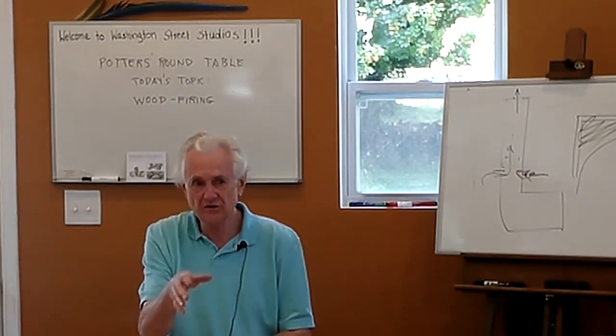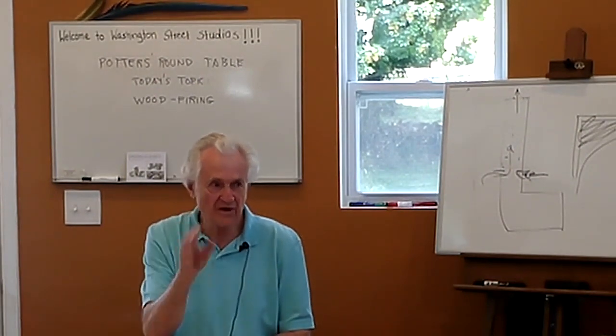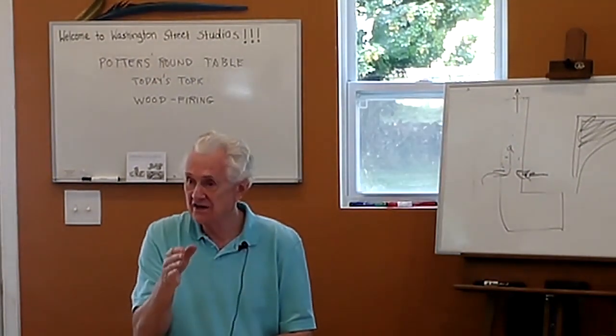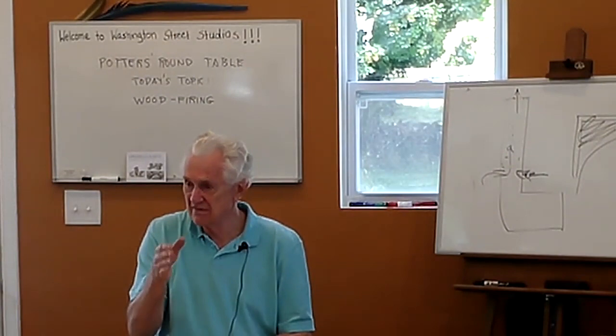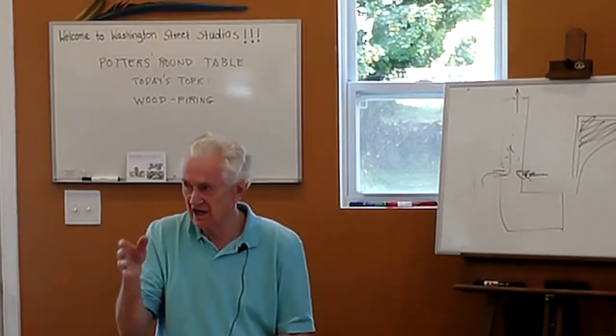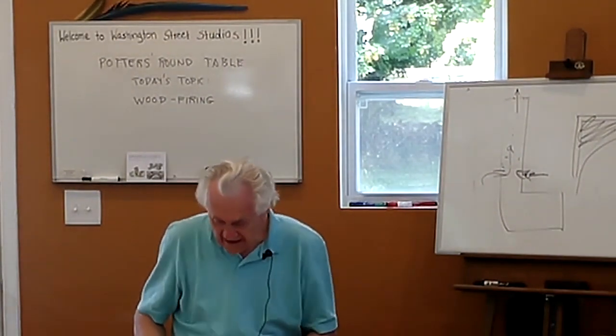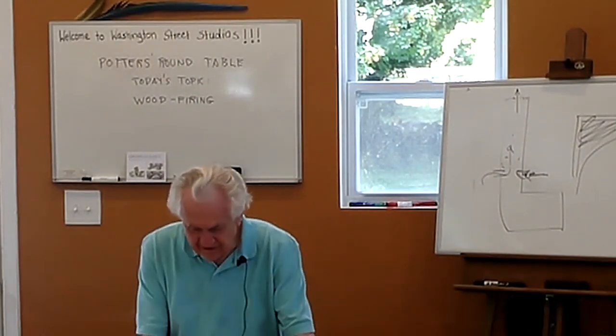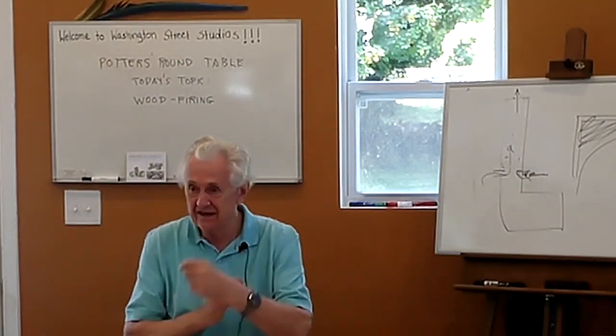And so if you're accumulating ash and it's sticking to the pot right up until the end of the firing, and you're not allowing enough time for that ash to melt without new ash landing, you can end up with crusty pots. And then the last thing, I've got a couple more things, but the last thing would be pots slumping in the firing.